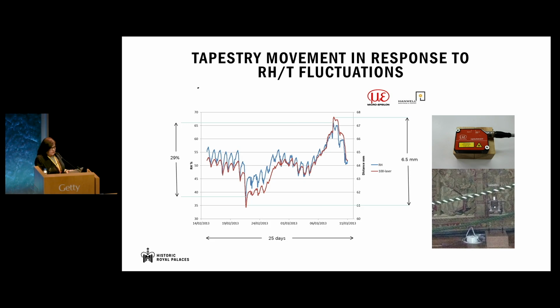To do that, we used a laser sensor, which we positioned at the bottom of the tapestry, and the laser was tracking the changes in height, the distance between the sensor and the edge of the tapestry. In the graph, the blue line shows RH data, and the red line, the data from the laser sensor. And you can see very clearly how the tapestry responds to the daily environmental fluctuations over a period of 25